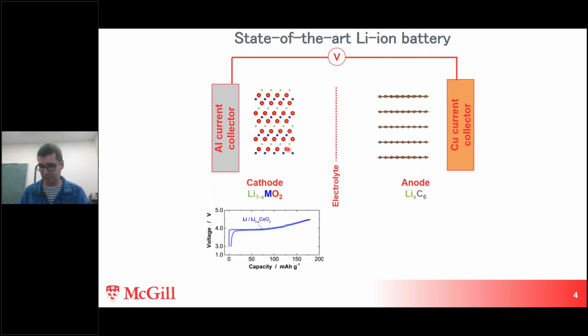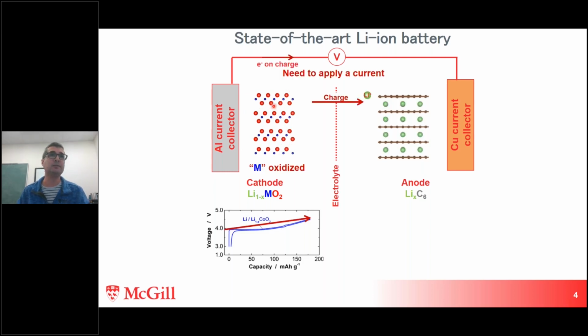So we have this cathode, and as we charge the battery, we take the lithium out from the cathode through the liquid electrolyte into the anode, which is graphite. So it's carbon, but it's not the most sustainable carbon. There's not an infinite amount of natural graphite that is battery grade. So there are sustainability issues as well on the anode side, but I'll talk mostly about cathodes today.